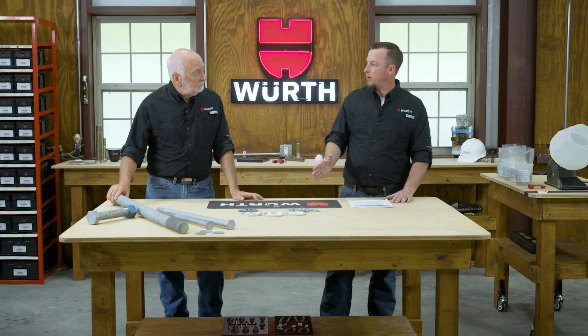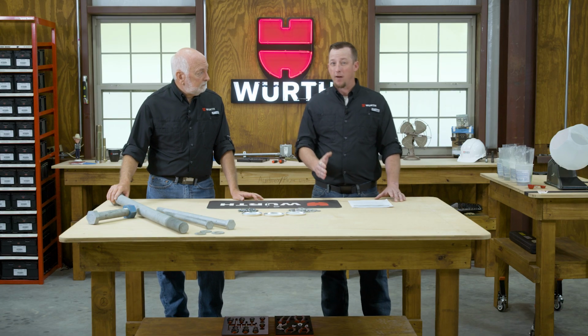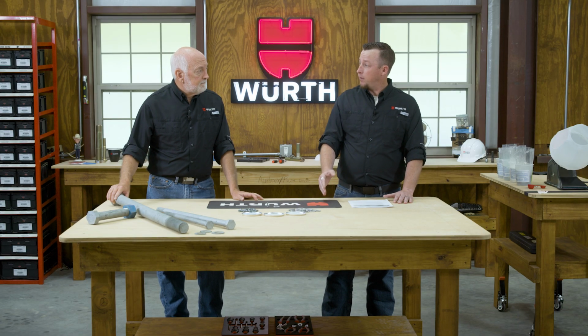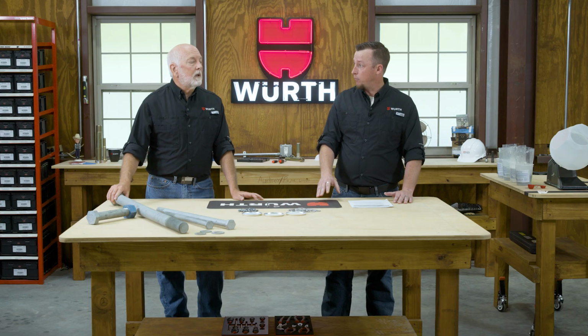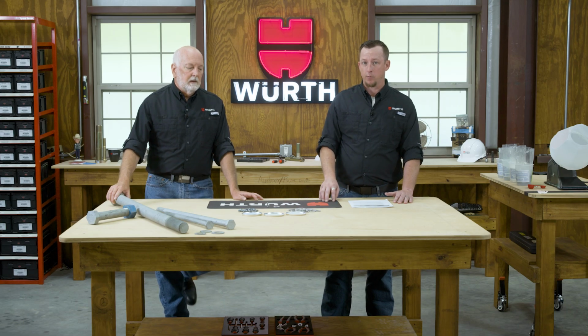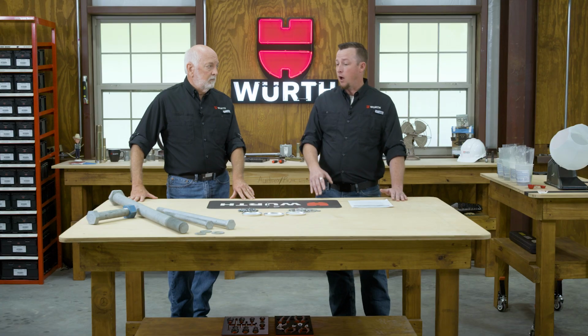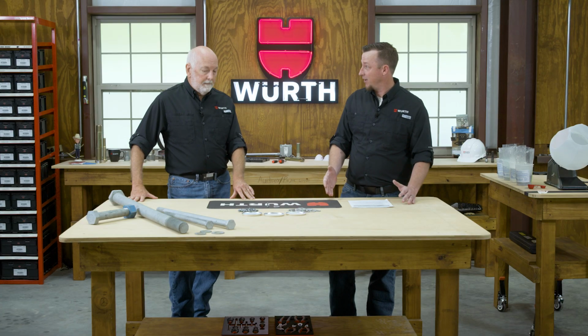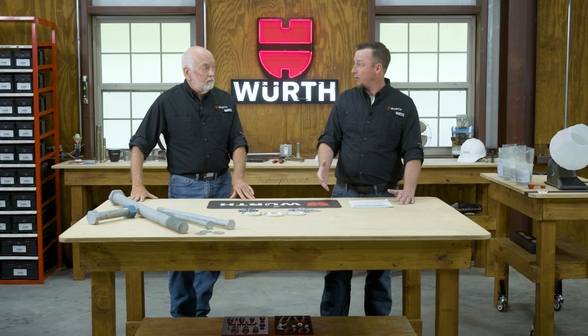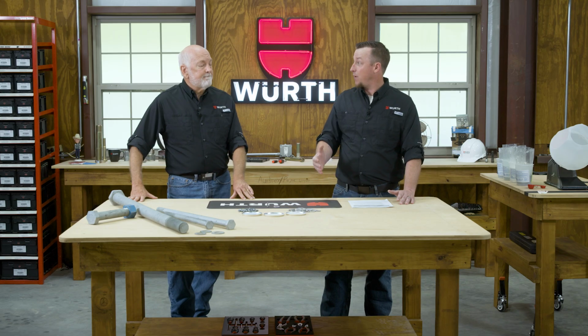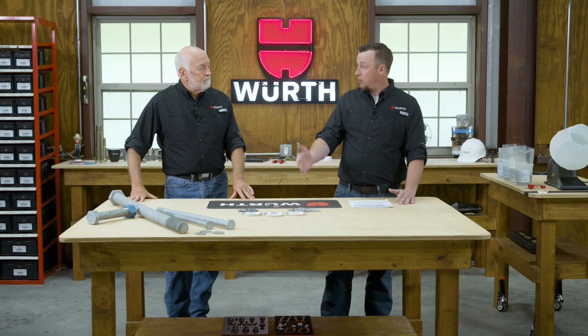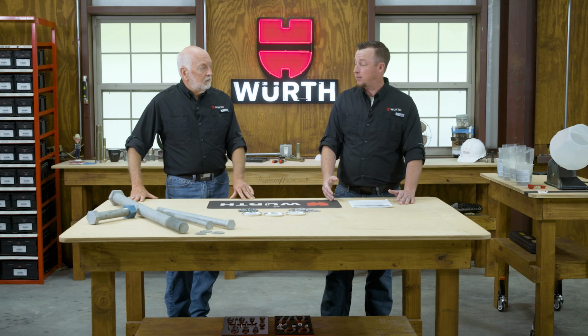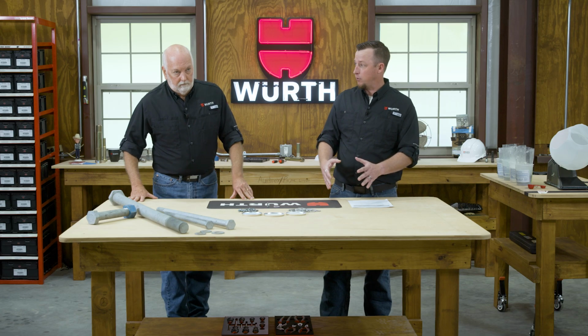Right. Now something to consider here of concern, just like we have the concern in electroplating, anything that's 39 HRC and above, we have to be concerned with hydrogen embrittlement. So we do not recommend hot dip galvanizing parts above 39 HRC. Correct. And the other concern I can think of, we're dealing with molten zinc. Yep. So we're talking about 800 plus degrees Fahrenheit. That could potentially affect the material itself. And that's a tempering temperature of the material.